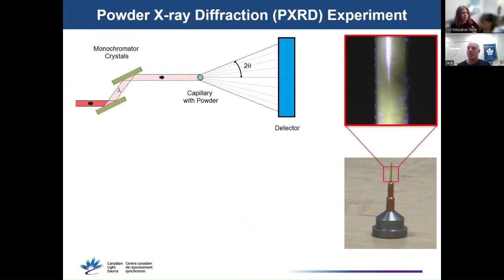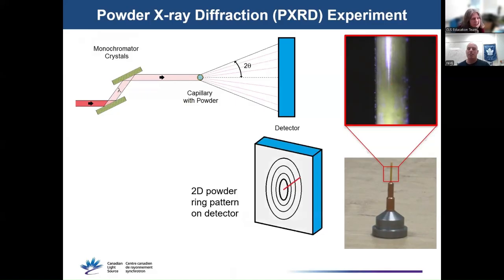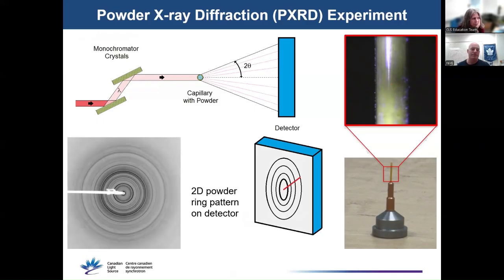This capillary at the top right is about 0.5 millimeter in diameter, and you can actually see some of the powder on the outside surface of the capillary. When we get diffraction from millions of crystals, instead of a pattern of spots on our detector, we get a pattern of rings because all of the different possible crystal orientations get merged together into one image. Looks something like this.